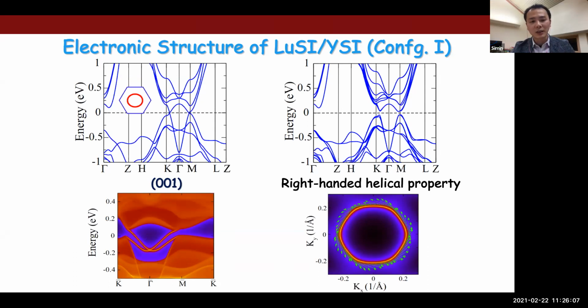That doesn't matter. You don't need the Dirac surface state to be at the Fermi level, because for this material, if the Fermi level cuts the surface state, you will naturally have circle-like surface states. You don't need it, unlike for Bismuth selenide, where in the ideal situation the Fermi level is at the surface Dirac point.